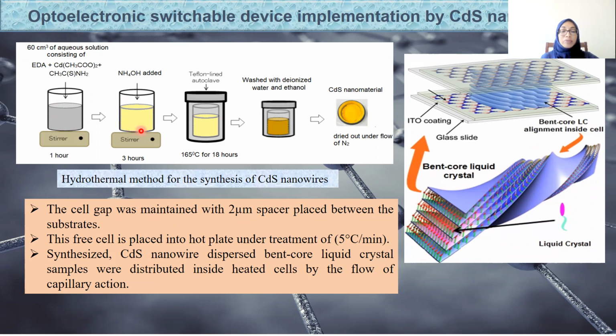This produced mixture was again left for 3 hours at constant temperature and magnetic stirring. Then it was transferred into a Teflon lined autoclave and maintained at 165 degrees centigrade for 18 hours. Then it was left to cool naturally in open atmosphere. The yellow precipitate was collected by centrifugal separation, washed with deionized water and ethanol, and it was then dried under vacuum for 5 hours at 65 degrees centigrade. The obtained sample was dried under continuous flow of nitrogen gas.